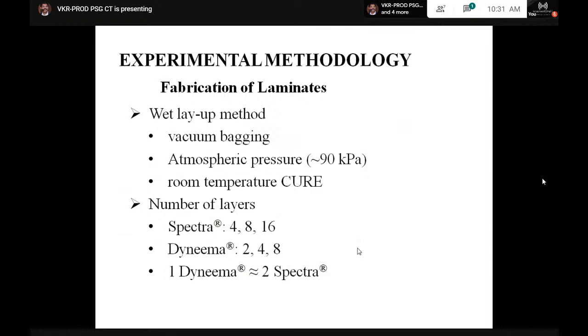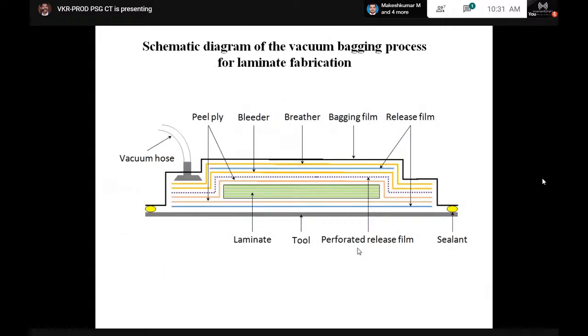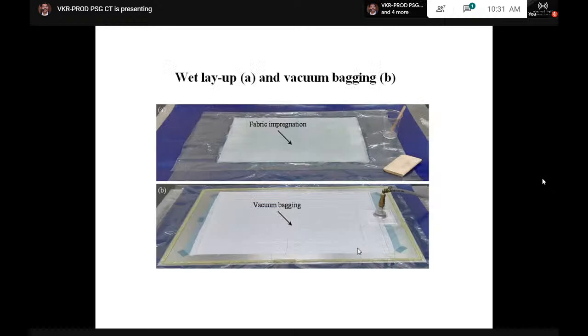The methodology is fabricating the laminate by a similar process, which I already told you, vacuum bagging, at atmospheric pressure, and it is cured at room temperature. Spectra and Dyneema are used, and one Dyneema layer is equal to 2 Spectra layers because of the variation in the density. This is a general schematic diagram of how vacuum bagging or vacuum infusion is done. This is the process.